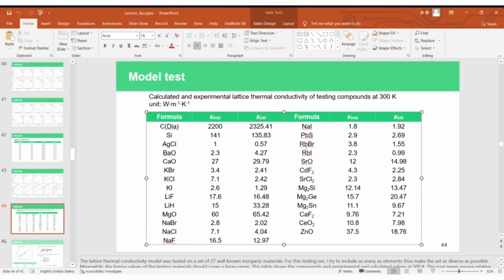Let's say, no, my model, we use phonon velocity and Grüneisen parameter to indicate, that's how to say, to indicate the harmonicity in the lattice. So actually I found the calculated lattice conductivity is very sensitive to the Grüneisen parameter we calculated.